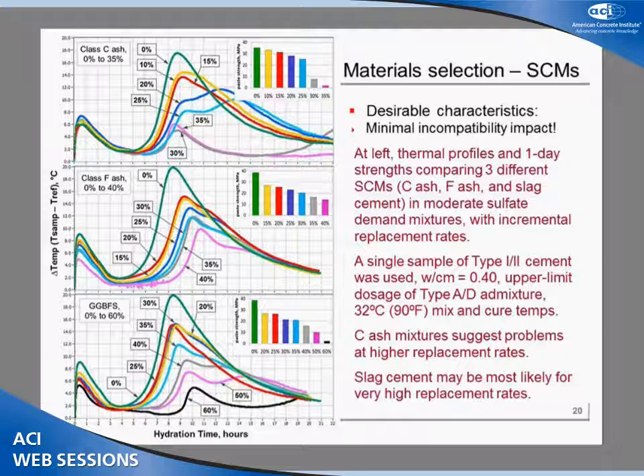And in this aggressive mixture, the Class C fly ash replacement rates much beyond, say, 15–20% are beginning to show up as distorted in the hydration profile history. And by the time you get to 30 and 35%, notice the one-day strengths, those materials are clearly experiencing what we refer to as incompatibility materials caused by insufficient sulfates available in solution. That being the case, as we explore mix development, we might expect to see problems out of this material.